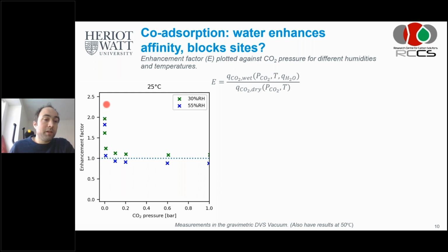So what you see immediately is that there's a declining trend. At very low partial pressures, and especially in the Henry regime, you have much more CO2 uptake in wet conditions than in dry conditions. That's very helpful because, for direct air capture, we have very low CO2 partial pressure. So at ambient conditions, you actually adsorb up to double the amount of CO2 in the presence of humidity. So that's fantastic.